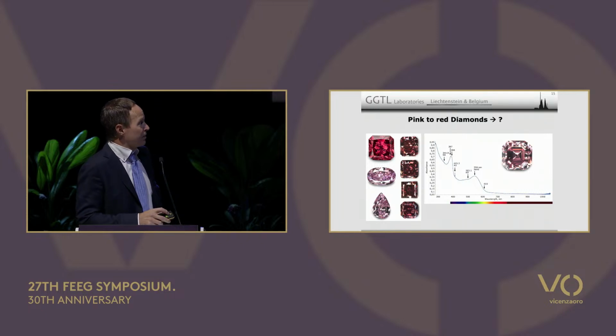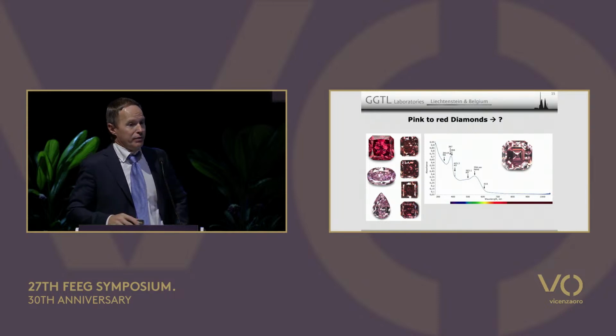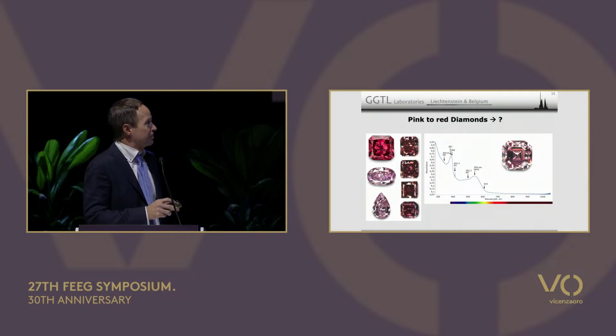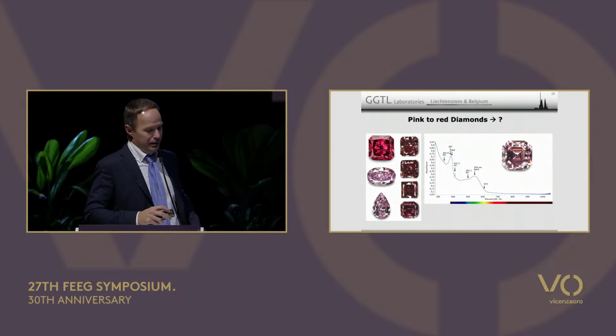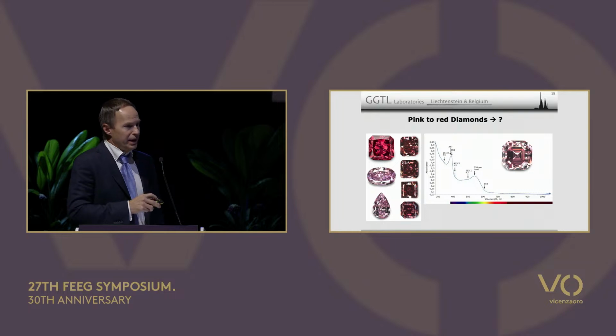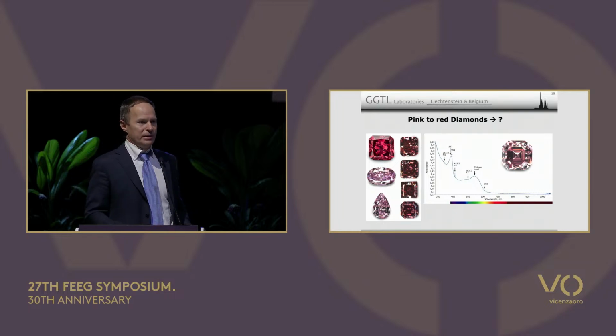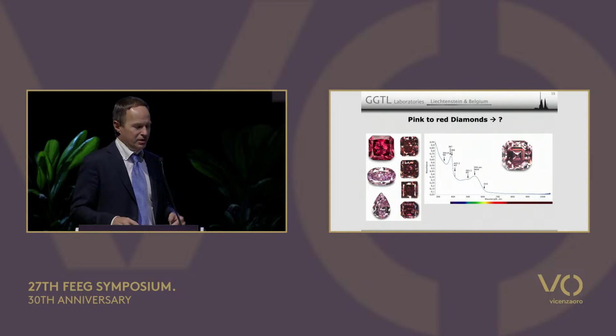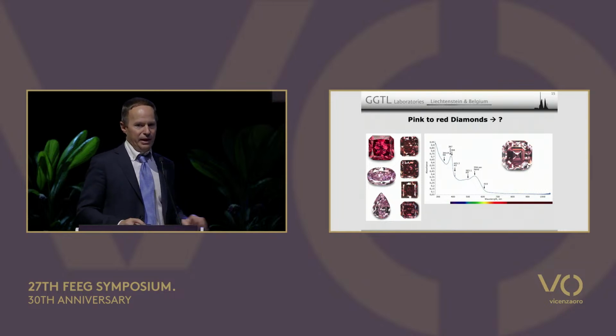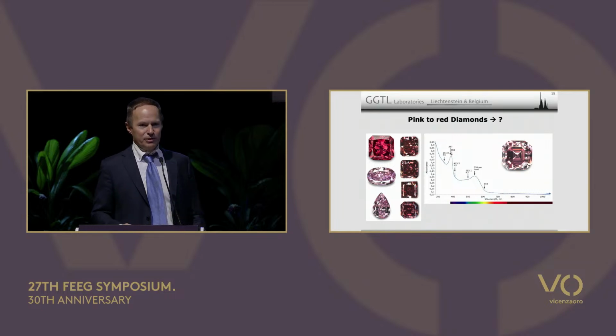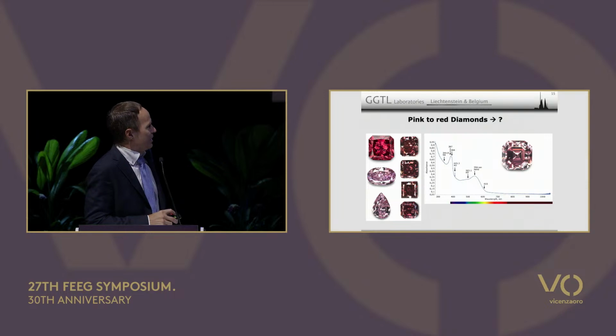So pink to red. Pink to reds are also colored by a continuum, but overlaying the continuum is a much stronger band at around 550 to 560 nanometers. Plus, many of them also have this unusual doublet here at 390 nanometers. Pink to red is exactly the same. So if somebody tells you red is much rarer than pink, that's just a darker pink. And if you have seen reds in the market, some of the deep pinks you'll see are actually prettier than the reds. And some of the reds we see, I'm like, okay, we wouldn't grade this as red. But it's always a question of definition.